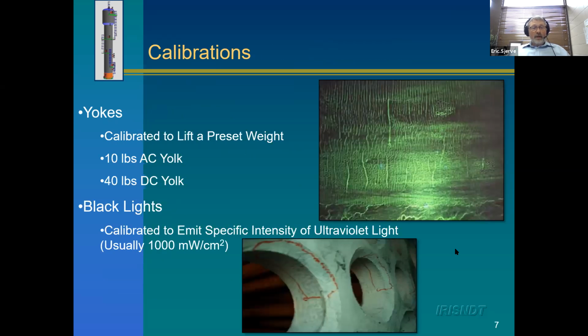With calibration, there's two parts to it. We have to calibrate the yokes. So that just has a magnetic field. So those yokes, if they're working properly, they can lift a certain amount of weight. So that's when, before a technician goes out and does this work, they calibrate based on the amount of weight. That has to be able to lift that amount of weight. And then the black lights, which are the ultraviolet lights, have to emit a certain density of radiation. So you have to have enough ultraviolet light to see the defects. So that's what the technicians will do before they go out. They'll calibrate those and they'll be on the report that they meet calibration standards.